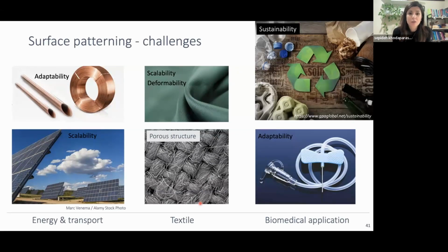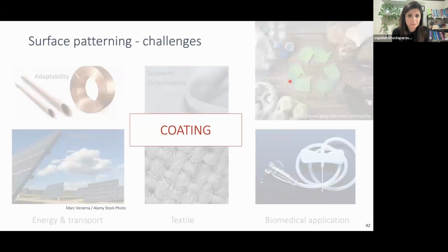For textile, it's even more complicated because these are multi-scale materials and they need to keep their deformability, and you still need to think about scalability. When you go to biomedical applications, very similar to the other cases, you still deal with curved surfaces. Although we've been thinking a lot about durability of these surface structuring techniques, the majority of the materials that we want to have surface structures on are actually single-use materials that have very short lifetime. So besides durability, we should think about sustainability of the material and the method that we use for this kind of surface patterning.